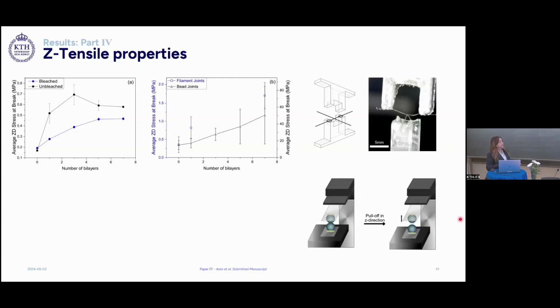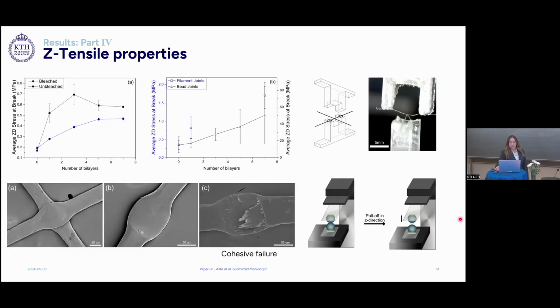To further investigate the effect of the treatment on the strength of the individual fibers, we developed a new method to measure the Z strength of the fiber joints using the CNF filaments. And we compared it with the data from the joints of the cellulose beads, since they're also pulled off in the Z direction. And we see that we have a similar trend, where we have an increase in the joint strength after LBL treatments. The filament joints were imaged with the SEM before and after separation, and we can see that the LBL treated joints resulted in cohesive failure.